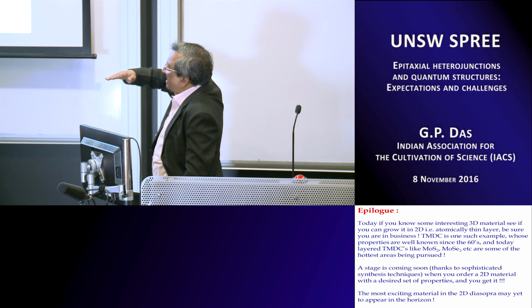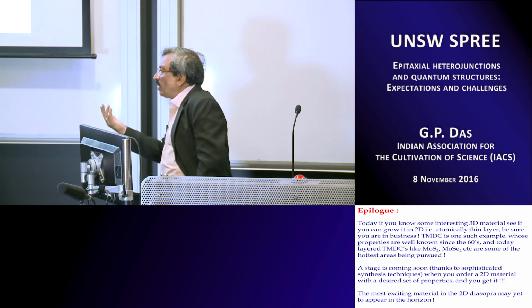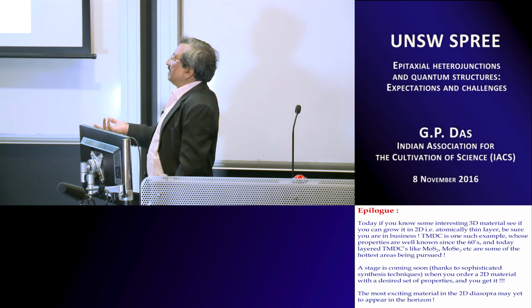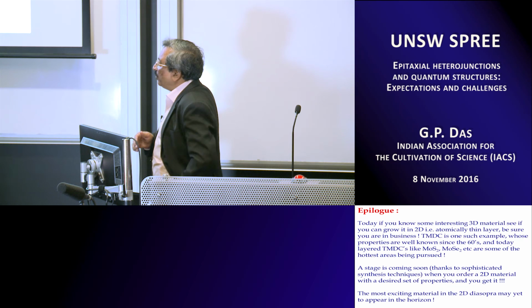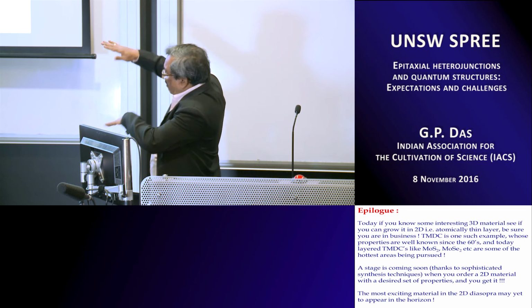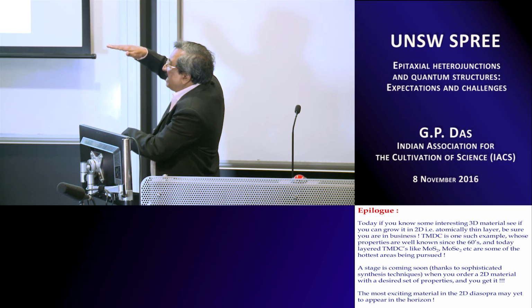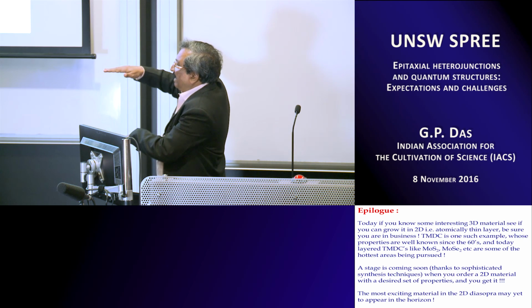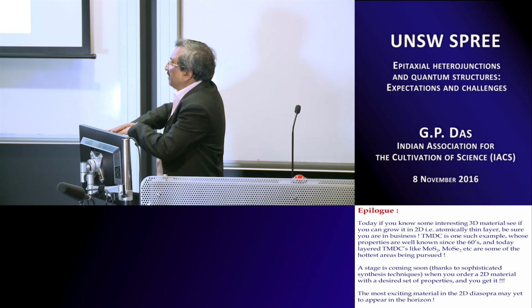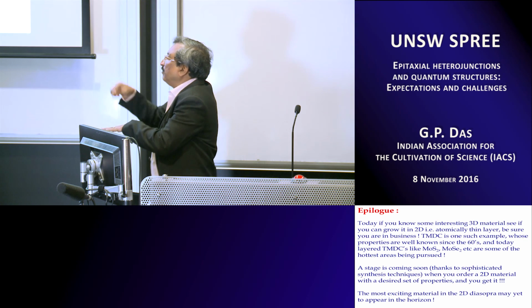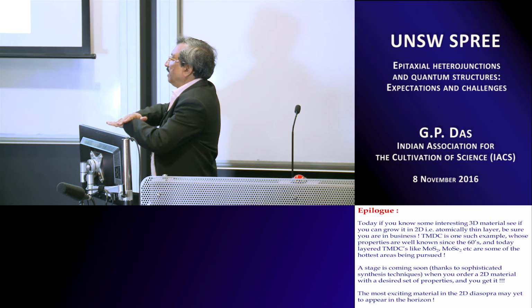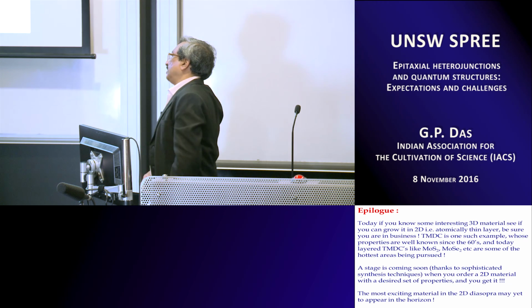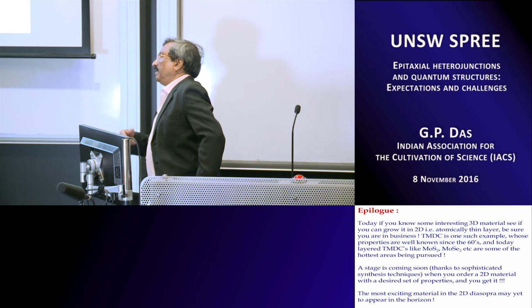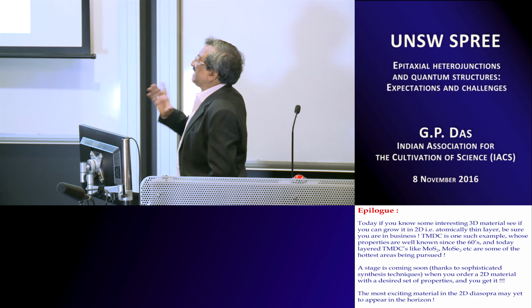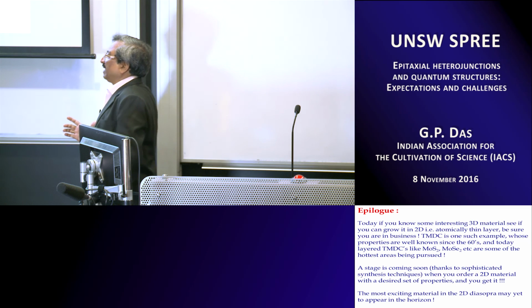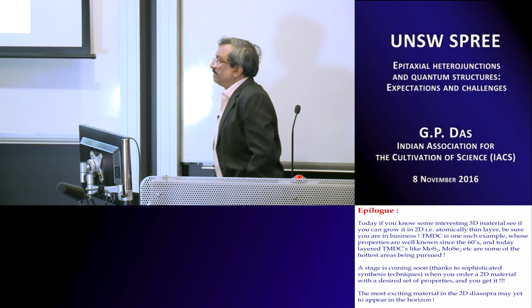As far as our calculation is concerned, we have kept a huge vacuum on the top. What you call ultra high vacuum, in the terminology of a simulation person, is that we create a vacuum in a well defined way, in such a way that there is no way the surface atom has any other foreign atom with which it can interact. So it's a completely pure surface that we can simulate. These are called slab calculations. It's a time consuming calculation, but we can do it. Yes.